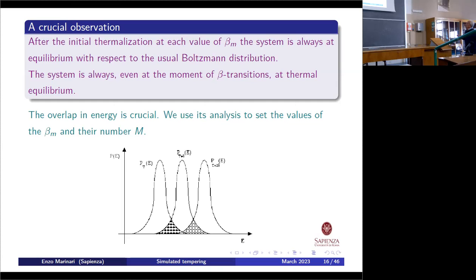The crucial observation is that after the initial thermalization, that as usual you have to do at each value of beta, the system is always at equilibrium with respect to the Boltzmann distribution restricted to this value of beta. Even at the moment of beta transition, the system is at thermal equilibrium. I'm very proud of this figure because that was done with our Macintosh of the time. You recognize it because these were the patterns you could use on this Macintosh, right? You would always put these patterns in order to color, and you were typically very proud of it. I could have redone it, because it's pretty awful the way it is done here, but I am very affectionate to this picture.